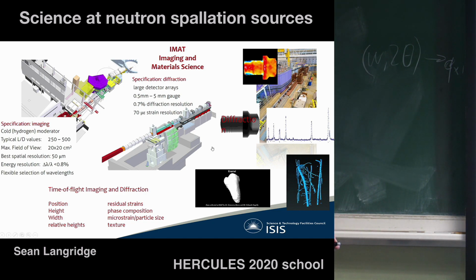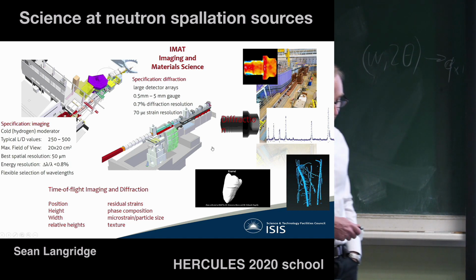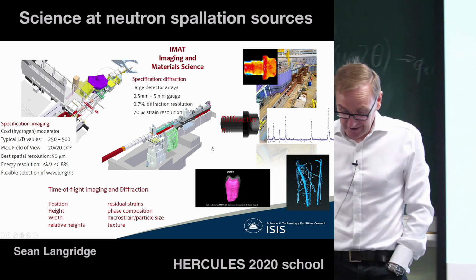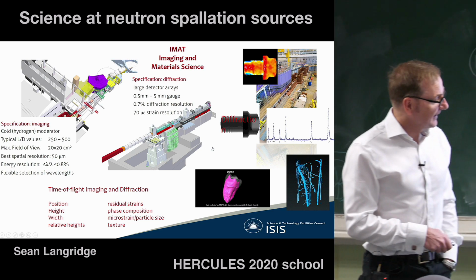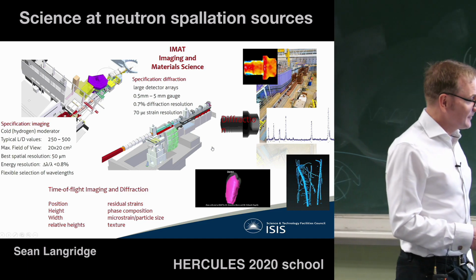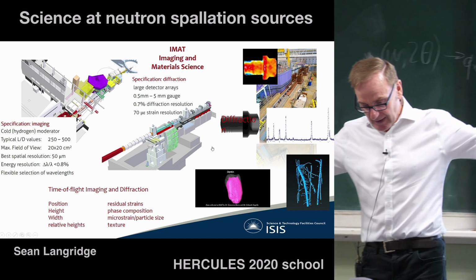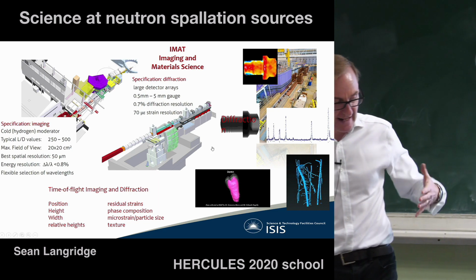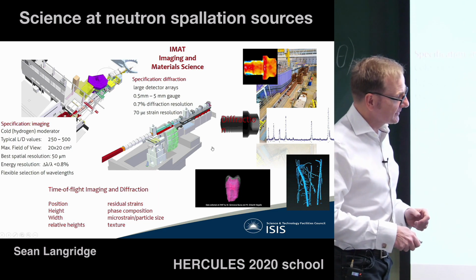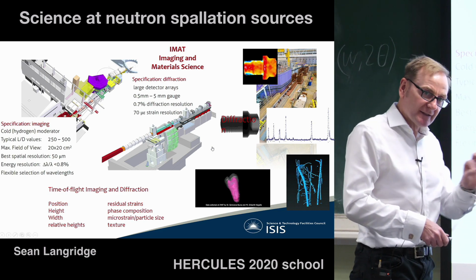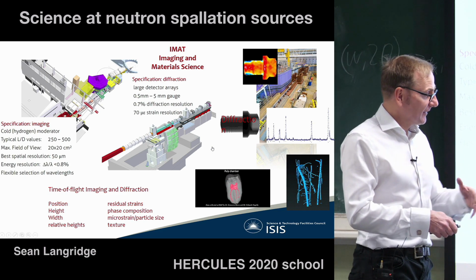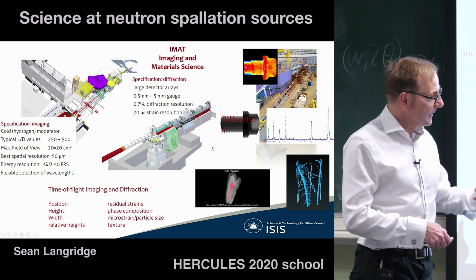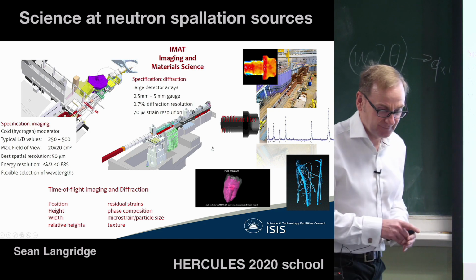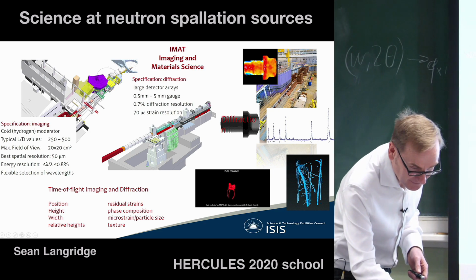This is some data from, literally, one of our instrument scientists, Dr. Genevieve Burka. She went to the dentist with a problem with her teeth, had a wisdom tooth removed, asked the dentist if she could keep the tooth. And so, of course, as you naturally do, you image it on the beamline. And this is the power that you can do with neutrons now. You can actually do imaging, and of course what we're using here is because we have a band of neutron energies, we can look at the energy dependence of absorption of a sample and not only get the spatial resolution from our detector, we can actually use the energy dependence to look inside these samples as well. So yeah, how to experiment on yourself without any ethical issues.